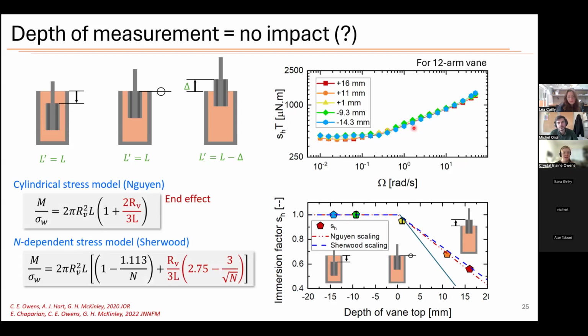And what this means actually is that if you want to see what's happening, ketchup is very opaque. So if you put a vane all the way inside, you can only kind of see the surface move. But if you're comfortable knowing that no matter what depth the vane is, you're still measuring the same thing, that means that we can insert a vane halfway through and look at the visible surface. And that would be equivalent for this material to being able to actually see a cross-section within the other case.